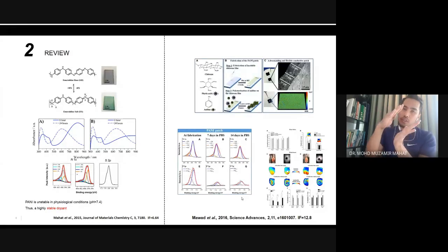After we put the polymer to connect the two parts, the broken tissue improved its rhythm after we electrically stimulated it. So this is a fantastic observation, a promising result showing that this polymer, this plastic that is electrically conductive, can improve the system of the heart, especially for a broken heart.